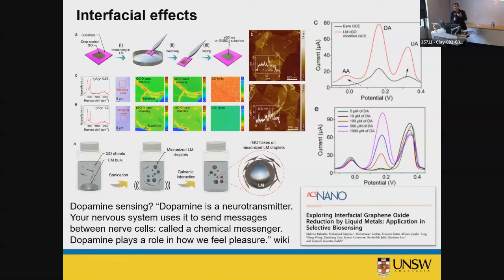We did electrochemical characterization. We realized maybe we can use this for sensing. So we use it for dopamine sensing. This example shows how we get selectivity. We have uric acid and ascorbic acid. If you do this sensing on the surface of graphene oxide, carbon surface, you can never tell the difference between the peaks of these groups. Now, because of using liquid metal at the core, we realized that we could push two of the peaks to each side, and as you see here, it became very selective at a specific voltage to dopamine.